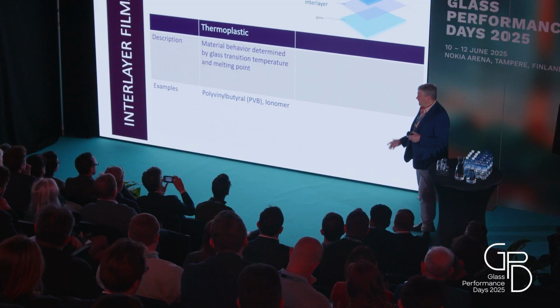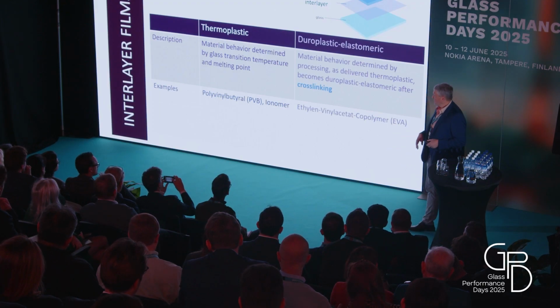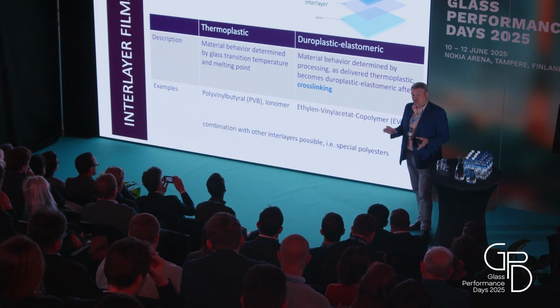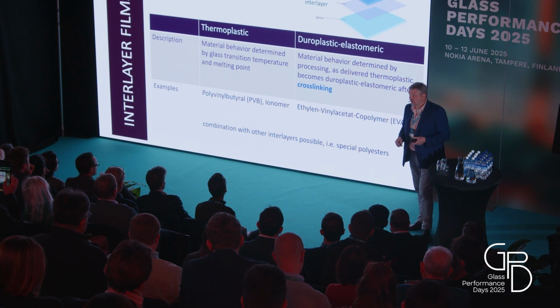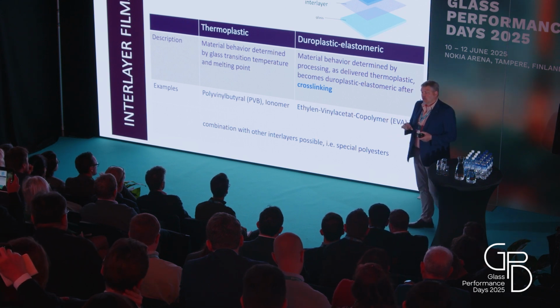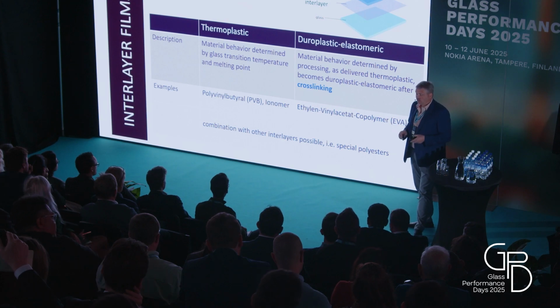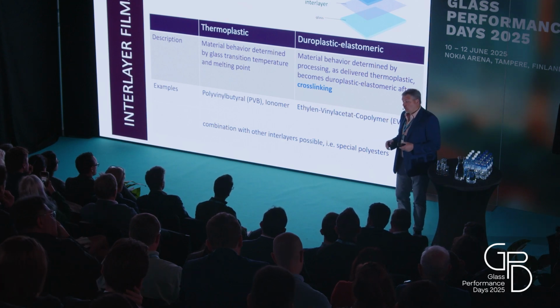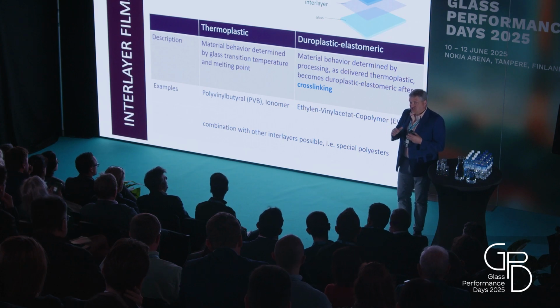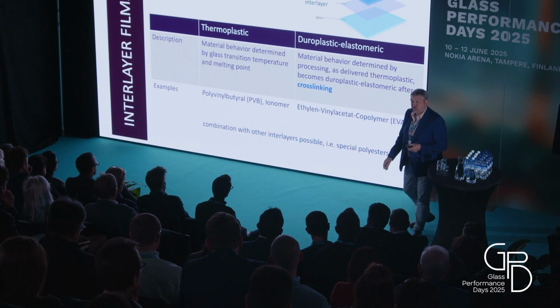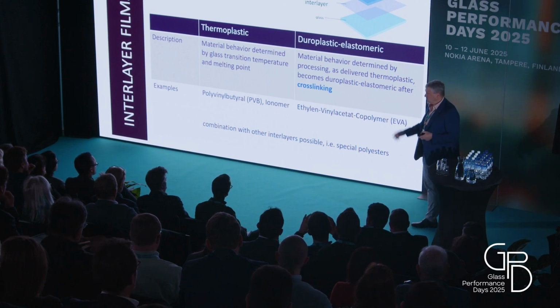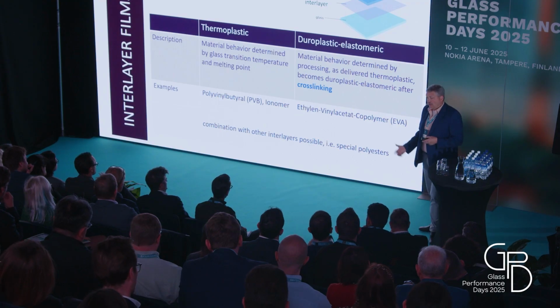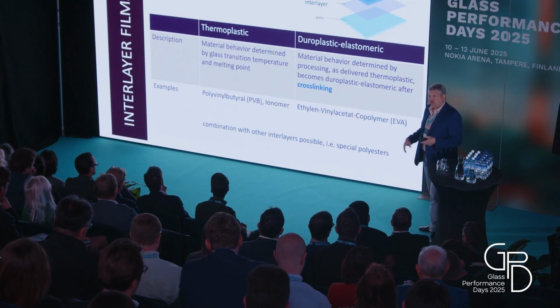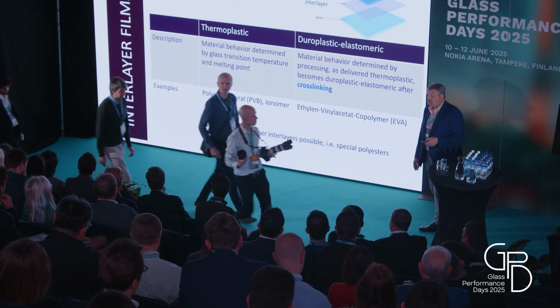Compared to this, if we go to cross-linkable interlayer films, they behave slightly differently. If you get them, the material looks the same as a thermoplastic film. It behaves like it is, the touch is the same. The difference is in the processing. There are some additives inside that make these films cross-linkable, and the process we're talking about is the cross-linking process, and this changes the material properties. An example for this is the so-called EVA film made of ethylene vinyl acetate copolymer. And of course, there are some combinations possible with other interlayers for making stiffer, for changing properties, and so on,